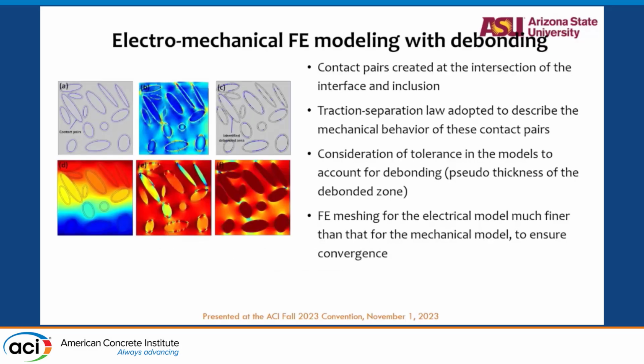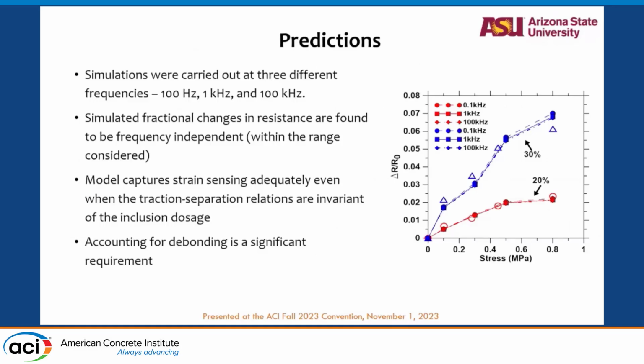And once the cohesive zone was introduced, it was based on a certain percentage volume. For 0, 10, 20, 30, 40 percent, we kept the parameters similar, and we saw that the pseudo thickness, the value considered for the cohesive zone, did not need to change between these different percentages.